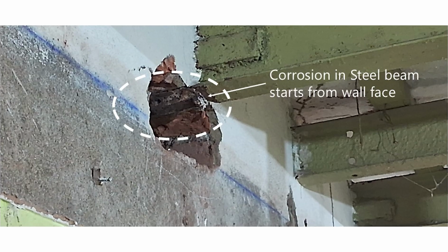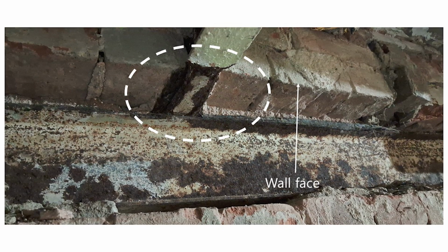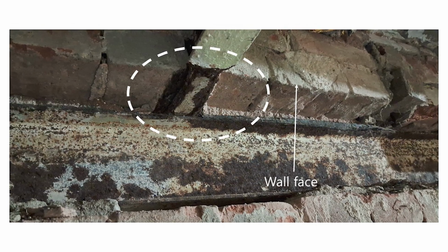The residential buildings constructed in the first half of the 20th century are now about 100 years old and under serious pressure of thorough maintenance and rehabilitation. Considering the roofing elements, the most common problem noticed is corrosion of steel beam. Interesting fact is that it normally starts from the bottom flange where it rests on the masonry wall. The other noticeable issues are termite attack on wooden battens and cracks on tile joints.